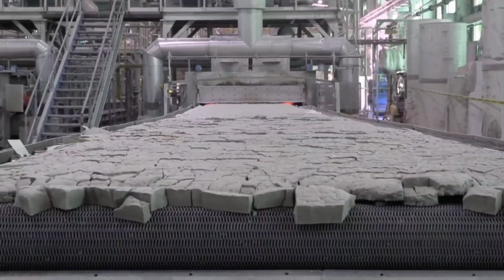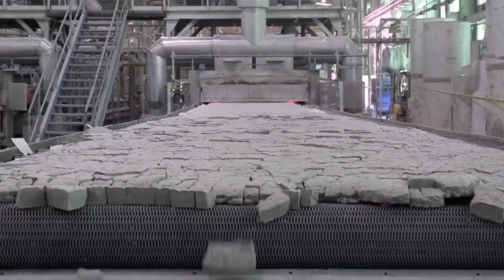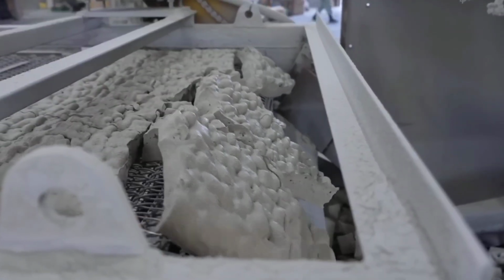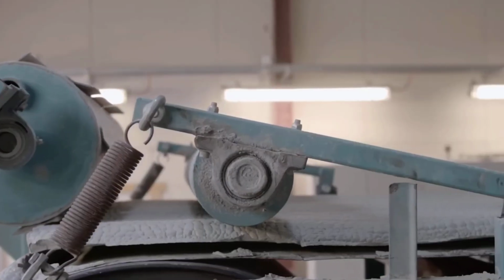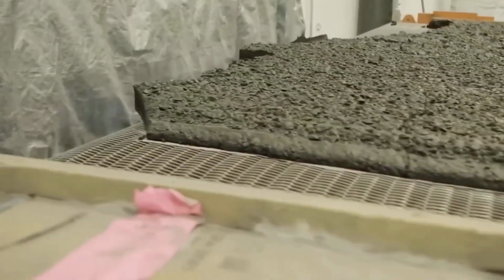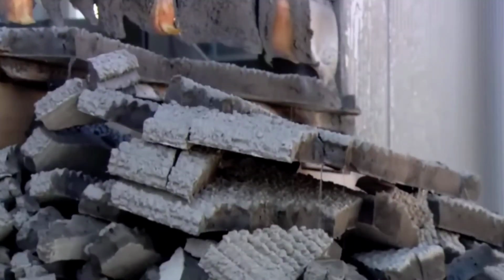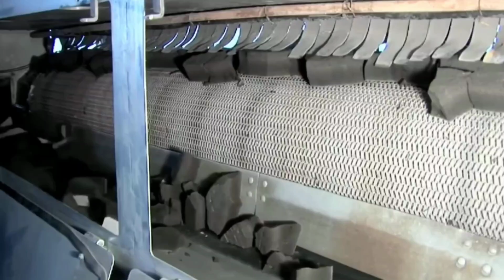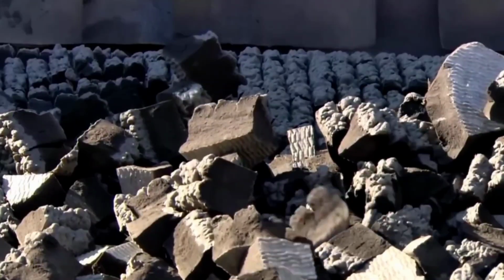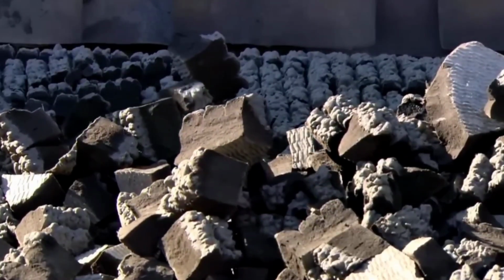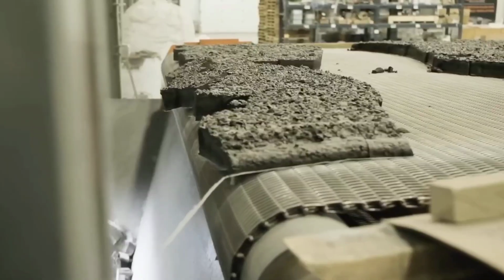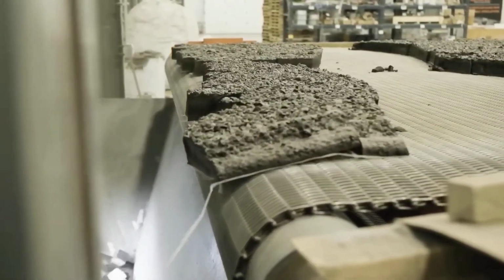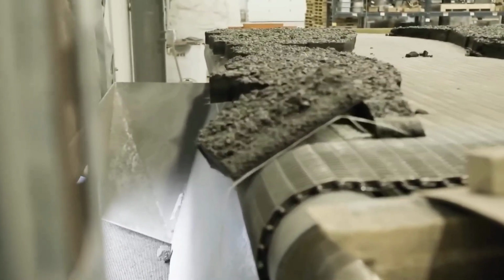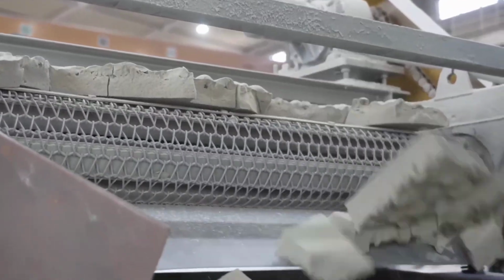foam glass block. The entire slab is placed onto a vibrating conveyor equipped with offset rollers that generate a precisely calculated torsional and mechanical vibration, typically between 20 and 40 hertz. Under this motion, the foam glass naturally cracks along internal stress lines formed during melting and cooling. These lines are intentionally engineered by controlling thickness, airflow direction, and furnace temperature, allowing the block to separate cleanly along predefined grids without the need for cutting tools.